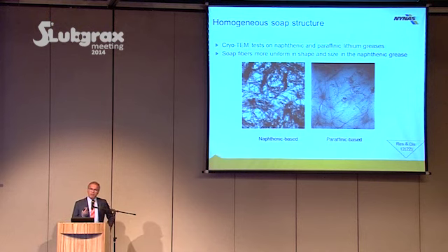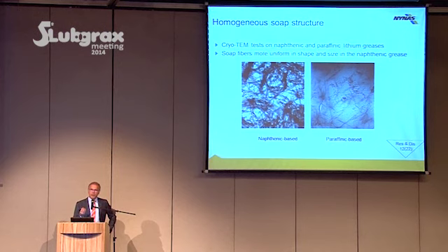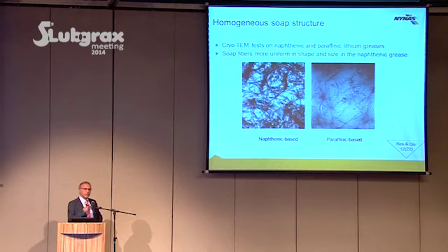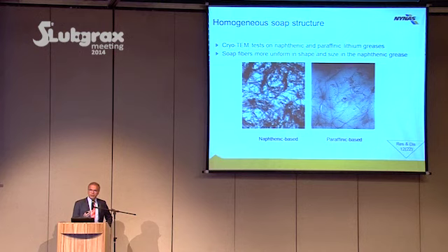This is the reason why when you use naphthenic oil, at least partially, you need less soap. On the left side, you have a picture, the same picture, with fibers or soap, if you would like to call it, which is much more dense and thicker. On the right side, you have the same soap manufactured in a group 1 paraffinic oil. The consequence is, if you want to match the consistency of the grease on the right side, made on the paraffinic oil, you need less fibers in order to reach this consistency. As you can see, we have lots of small black dots. These are also soap, but these do not contribute significantly to the consistency of the grease.